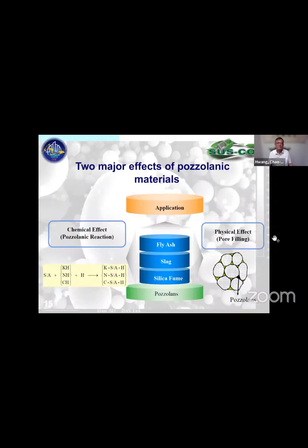Okay, next, please. So in Taiwan, in order to make fly ash very useful, we use fly ash not by replacement. No, we don't replace cement, because cement is cement. What we are doing is filling the pores of sand. Because of the particle size, we can fill the small voids. By looking at the physical particle size distribution, we know this material has a good gradation. So you put it into the voids, they can fill the voids and stop any penetration of water. That is the physical pore filling effect.